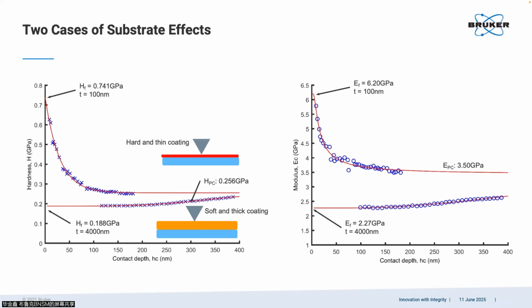I have these two typical cases for you. For these two cases, the substrate is exactly the same, and we have a very thin and very hard top layer. So we have the hardness trend with depth like this. You can see the hardness decreases very dramatically when the contact depth is going up. And this is the modulus, with similar behavior. Another case is a thick and softer top layer on exactly the same substrate. So the behavior is here. It's totally opposite behavior, and the tendency is not so fast because your film thickness is higher. So this is the idea. The key point is always how shallow we can get, and that is sometimes about how good our tools are.